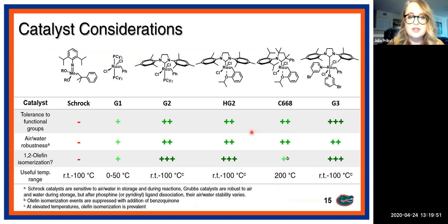So that leads me into talking about some catalyst considerations. So we choose catalysts that can achieve our metathesis chemistry under our desired conditions. Early work used Schrock catalysts to perform the ADMET polymerization. These are really wonderful catalysts if you're polymerizing all aliphatic systems. So they have very little 1,2 olefin isomerization, but they are very air and water sensitive. So this is really chemistry that happens in the glove box. And they don't have very good tolerance to functional groups, but they have beautiful precision if you're working with all aliphatic systems.